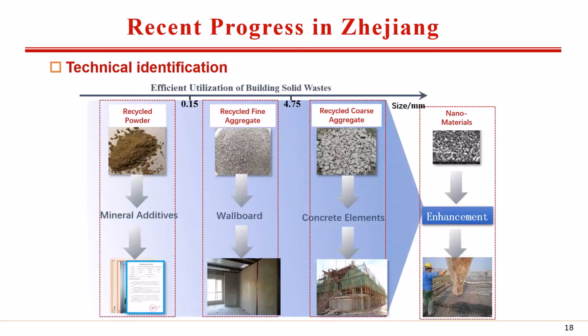The efficient utilization of building solid waste should be studied according to different particle size. This is the roadmap of our project. However, mixed recycled aggregate is normally very weak and has high water absorption. So we need to find an effective method to strengthen this kind of aggregates. In Zhejiang, we use nano technique. We call it nano enhancement.